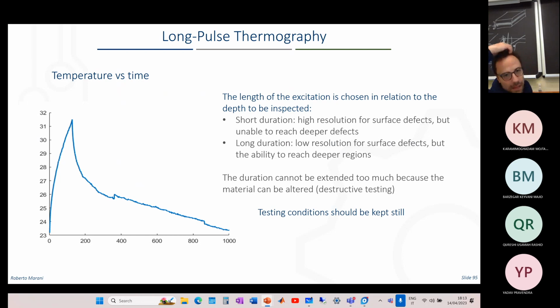For example, in this case, this is an actual measurement. There's a problem here. If you see your decay, well, it's actually kind of exponential. I don't know if this is taken from a defective region or a sound region. But there are two discontinuities in the decay at 400 and 850. These are due to somebody that was walking and is reflected by the target. So the reflection of the body of the person that was at 36 degrees makes the temperature higher in this small gap.